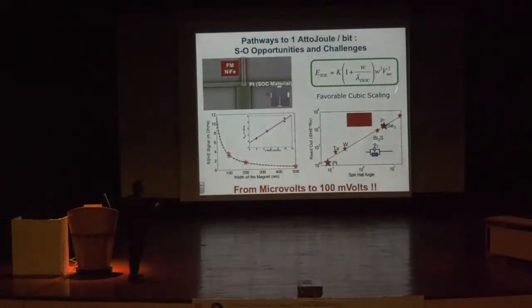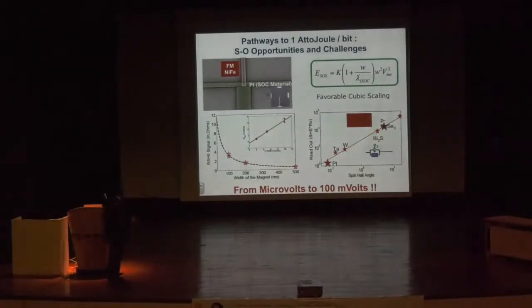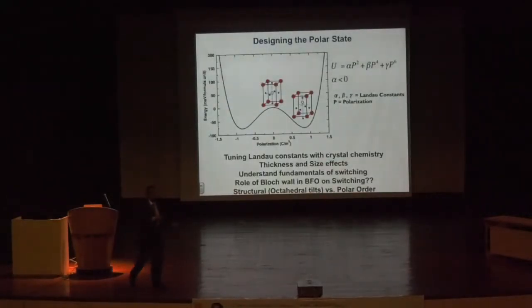The one thing nice about this is Sashi's calculation, that it goes as a cube of the lateral dimensions. So as I make the devices smaller and smaller, and indeed our data does show that as you make them smaller and smaller, the inverse spin Hall voltage goes up as a cube of the dimension. Now, coming back to magnetoelectrics. I'm sure you've seen this in textbooks. This is just the standard double well structure for a ferroelectric given by this classical Landau type approach. So you can now say, if I have to reduce the energy required to go from this part to this part, I need to tune this. I need to start to tune all of the Landau parameters.